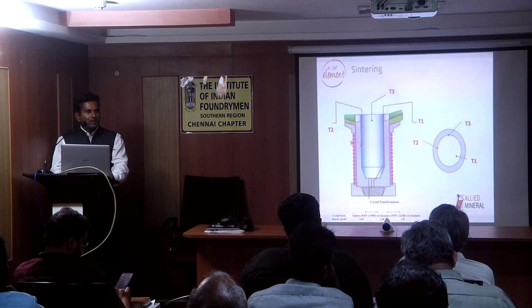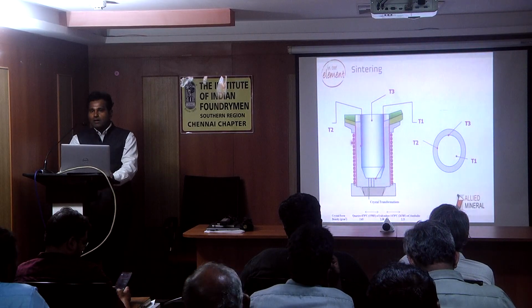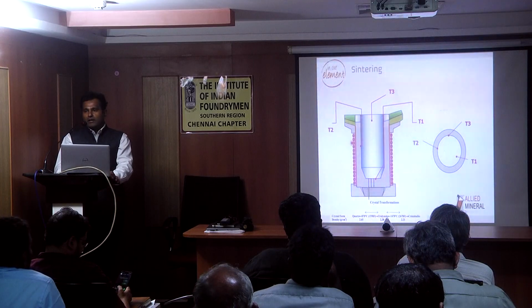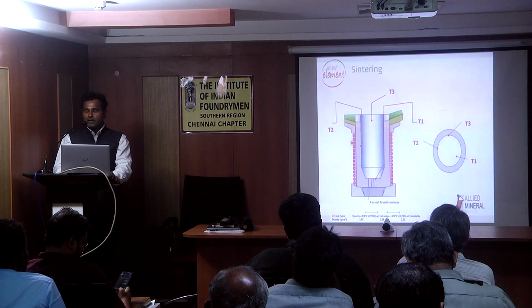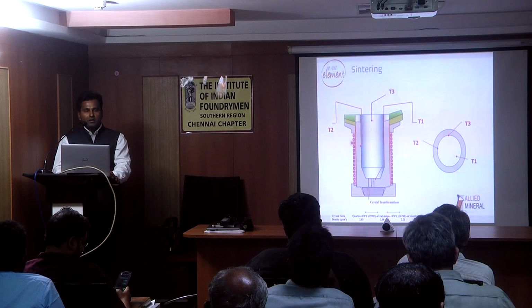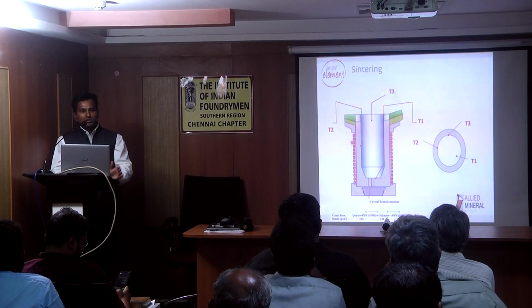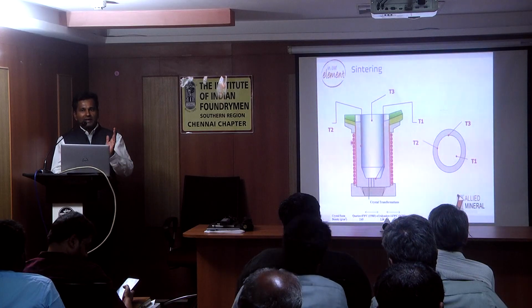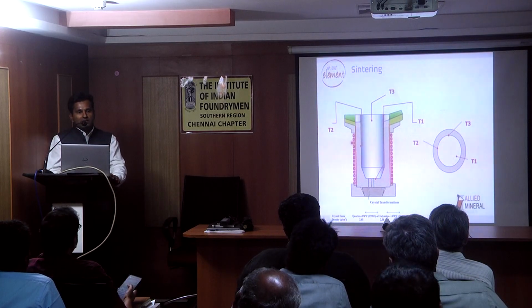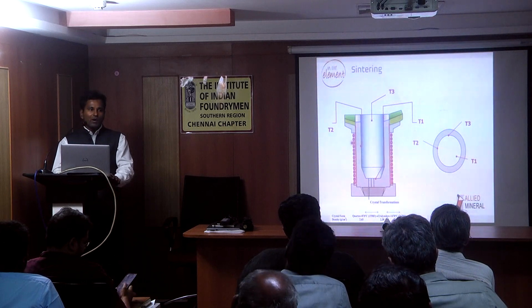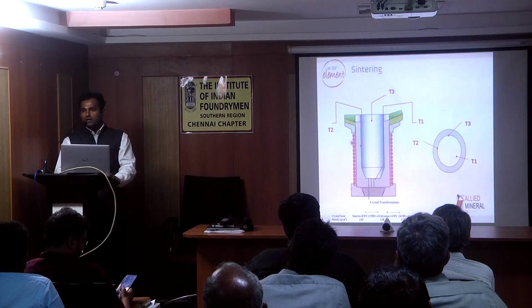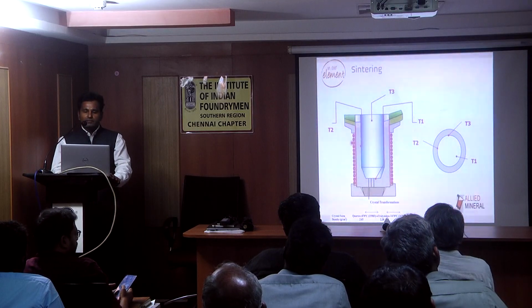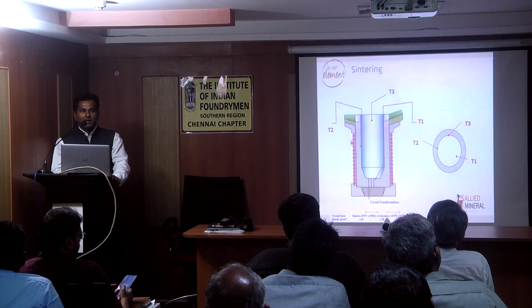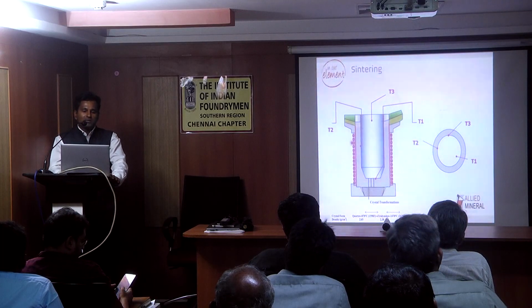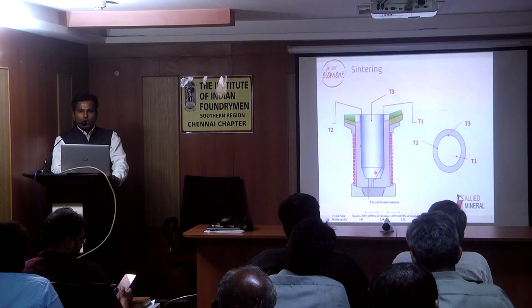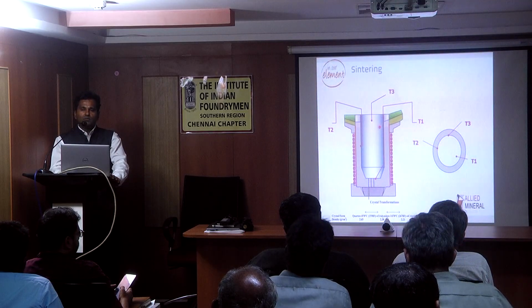And now we'll talk about sintering, and how sintering will affect your main lining life. Refractory understands only the temperature, so it doesn't understand the kilowatt reading. But as an age-old practice, people used to follow the on-off cycle and slow heating cycle. But how much kilowatt gives you what temperature, nobody knows. So we have to do an initial sintering based on the thermocouple values. Depending upon the furnace size, we recommend either 1, 2 or 3, maximum 3 thermocouples. The thermocouples have to be placed at the bottom, one half of the furnace, and 3/4 of the furnace from the bottom.